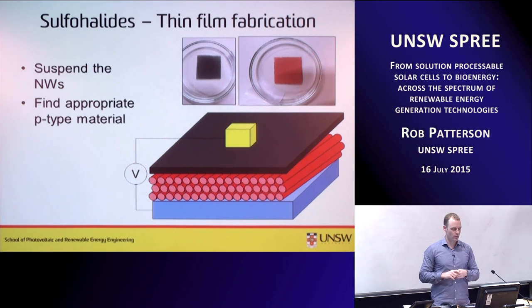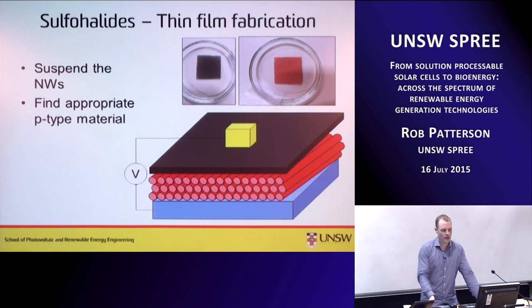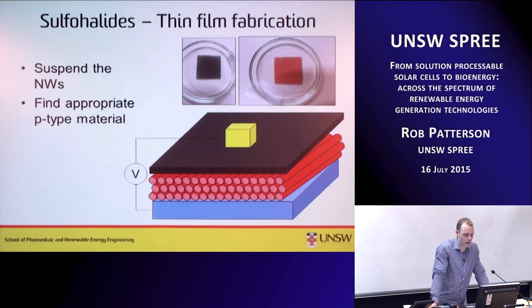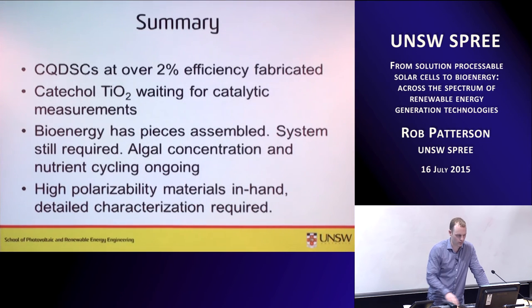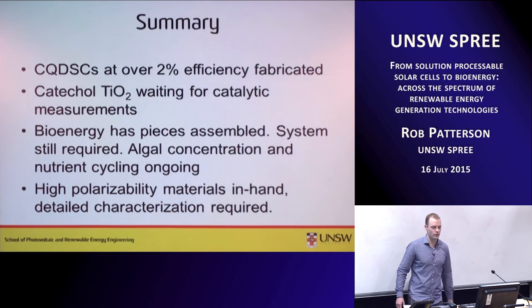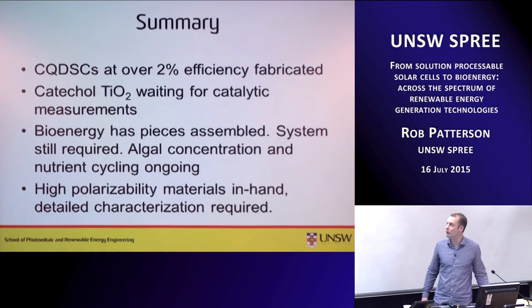In order to make solar cells from this material, we would have to find an appropriate p-type material. These materials are typically n-type. So that means that for the colloidal quantum dot solar cells that we typically make, the structure needs to be inverted. I don't think this is a big problem, but in solution it's never 100% straightforward. So we'll be trying to make solar cells from these, and hopefully I can tell you about that next time too.